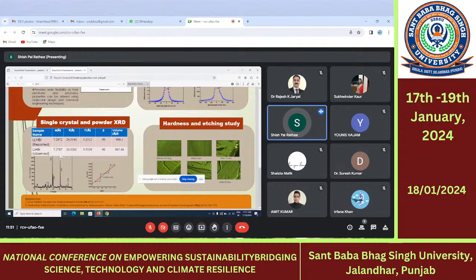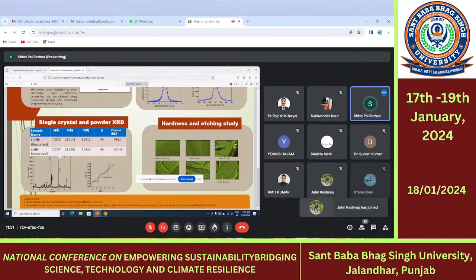This crystal is very useful. This crystal is a nonlinear optical crystal, and it has a very large value of second harmonic generation efficiency that is approximately 4 times that of the KDP crystal. And if we are able to grow this crystal with much more mechanical strength and also good optical transmission, we can say that this crystal can be a potential candidate for optical modulators and other electro-optic devices. Thank you.